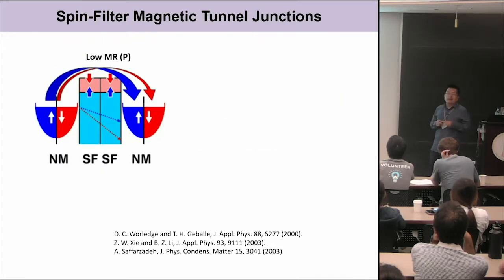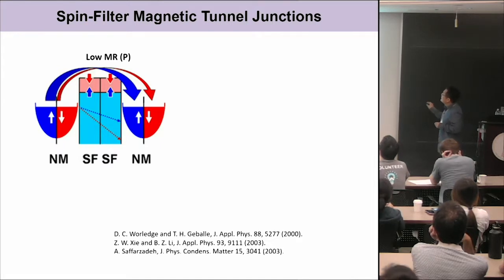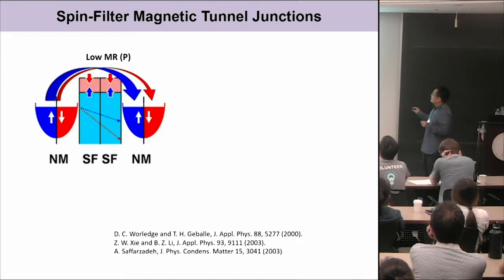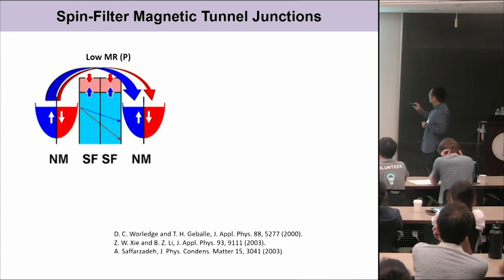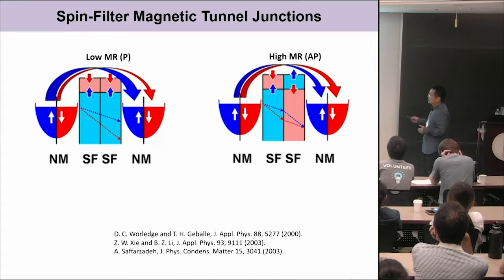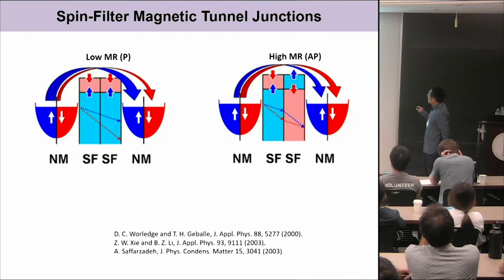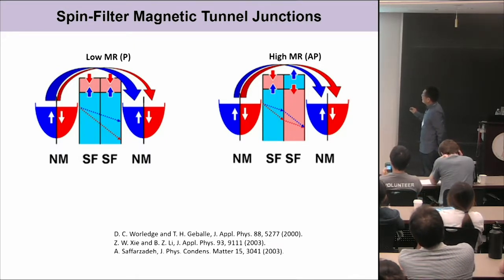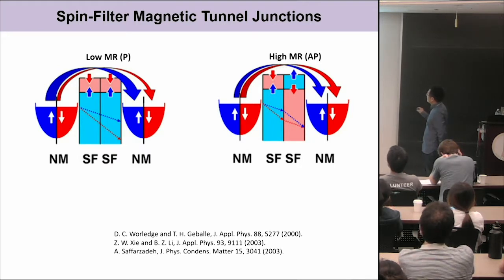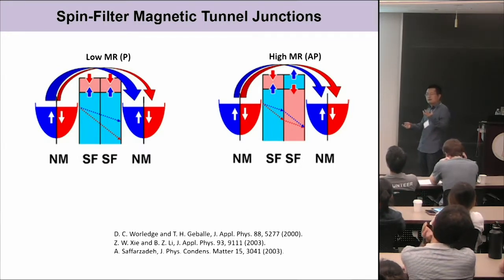Then there's another scheme called spin filter TMR. For this scheme, the difference is that the contact becomes non-magnetic, but the tunnel barrier is magnetic. In particular, for this tunnel barrier, imagine you have two spin filters. You can switch the system from these two spin filters aligned with each other or anti-aligned with each other. Then in this case, we can also realize tunneling magnetoresistance, right? But the challenge is, how can we get a magnet with this type of spin filter function? Basically, switching between aligned and anti-aligned configurations.